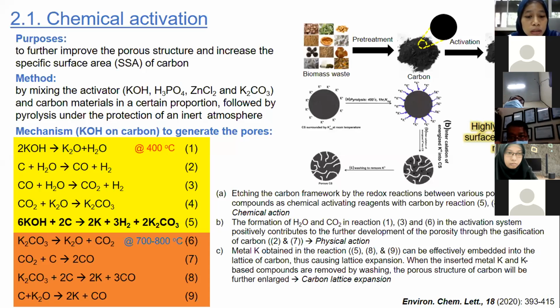Start from the dehydration of KOH to transform into potassium oxide at 400 degrees Celsius, and then carbon is consumed by the reaction of carbon and H2O with the emission of hydrogen gas, and potassium carbonate is formed by the reaction of potassium oxide and CO2. And then potassium carbonate significantly decomposes into CO2 and potassium oxide at temperature higher than 700 degrees Celsius and completely disappears at 800 degrees Celsius.